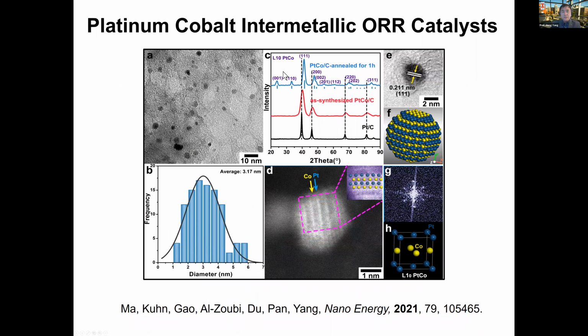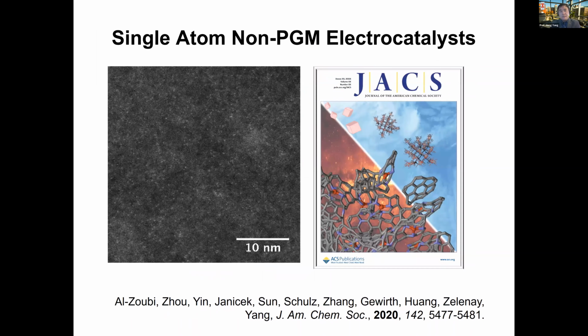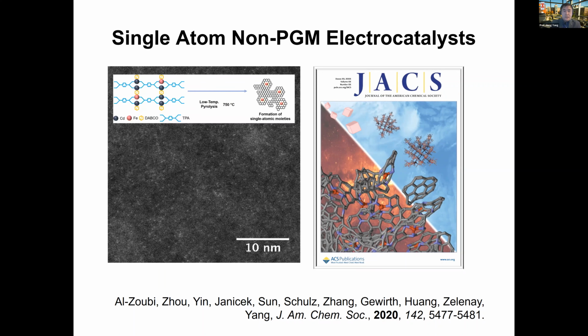as is evident in this diagram, the L10 platinum cobalt phase. As you can imagine, the particles we focus on are typically rather small, around 2 to 4 nanometers, and we try to maximize the formation of this intermetallic. There are fundamental issues in terms of how stable those intermetallics can be, approaching almost the limit of these particle sizes. The other aspect we also venture into in oxygen reduction catalysts is the development of non-platinum group metal catalysts, primarily focusing on single atom development. This is related to so-called MOF-based, i.e. metal organic framework based, or atomically dispersed precursor-based synthesis. That is the idea behind it.